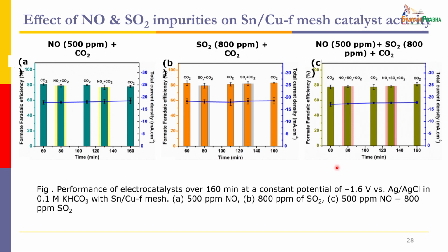So whether you have an impurity or not, the Faraday efficiency remained almost the same. That means the catalysts were tolerant to these poisons. So whatever we have, NOx, it is tolerant. So we did the same for SOx. First with NOx, next with SOx, then also with the mixture of both SOx and NOx. So both SOx and NOx were mixed along with the CO2. Then the reduction experiment was performed.